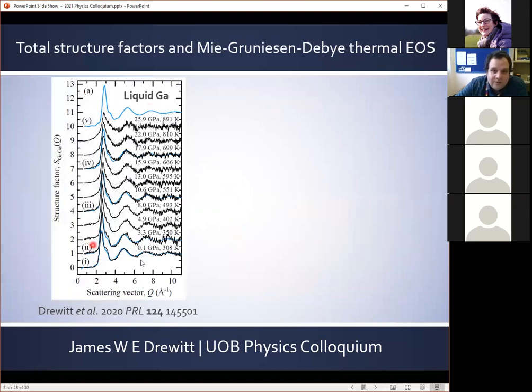So the power of the ab initio molecular dynamics technique can be assessed by its ability to accurately reproduce experimental measurements. And so here I show the high pressure structure factors for liquid gallium in black, and the ab initio simulations at corresponding conditions in blue. And you can see there's very good agreement between the simulations and the experimental measurements and the corresponding pressure evolution.